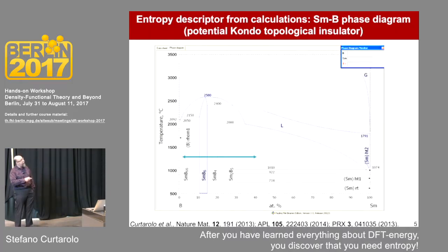So in this area, you have samarium boron 6, which means that you still have the geometry of samarium boron 6, but sometimes you have samarium 0.99 or samarium 1.1. You understand, right? So there is a range of solubility. Then this is the melting point. You see that it is congruent, because the maximum of the solid is the minimum of the liquid. So this is congruent, okay?